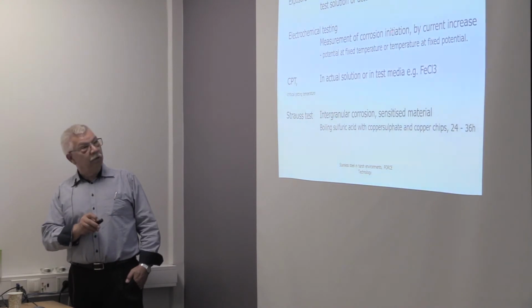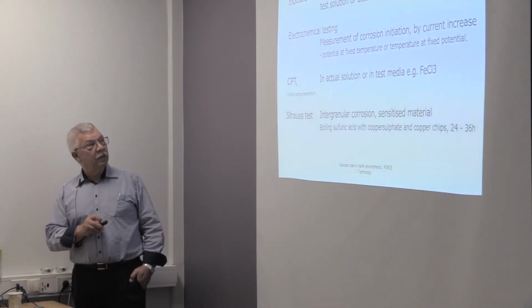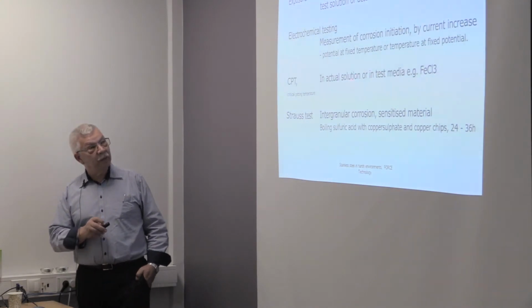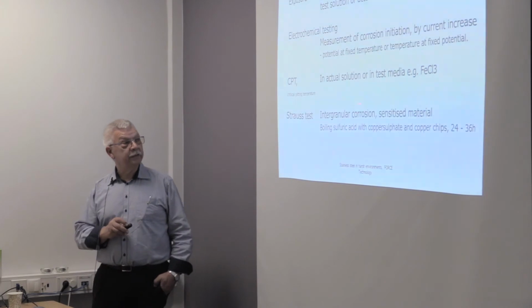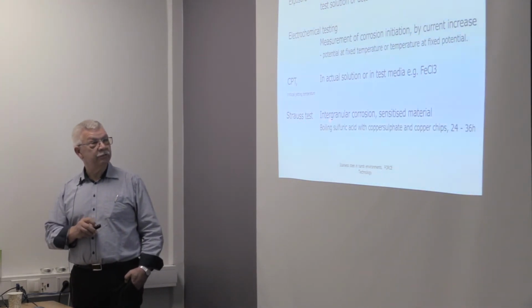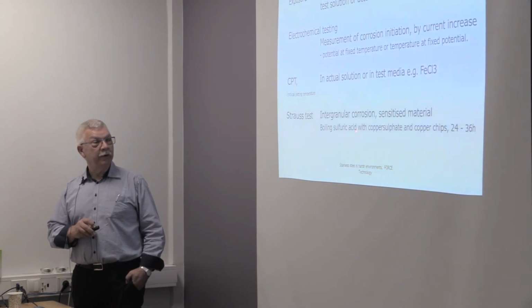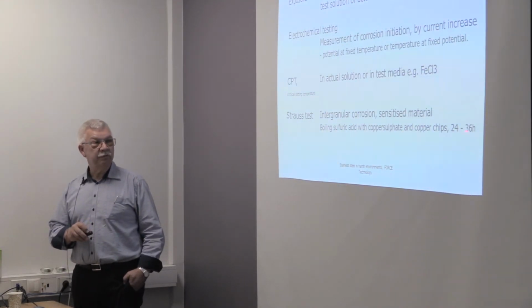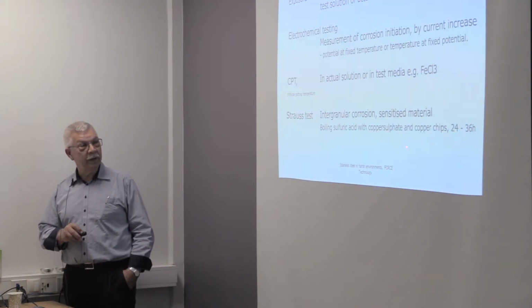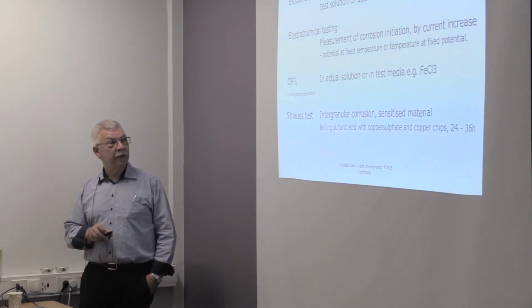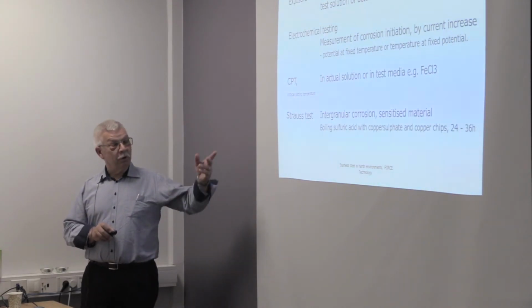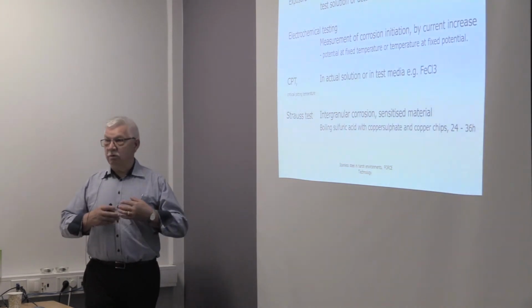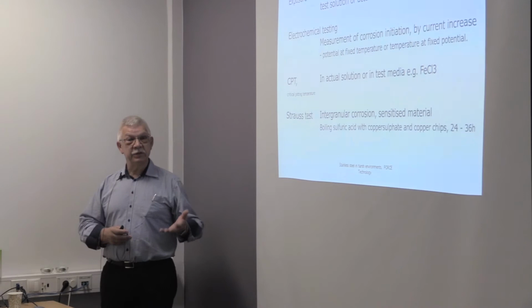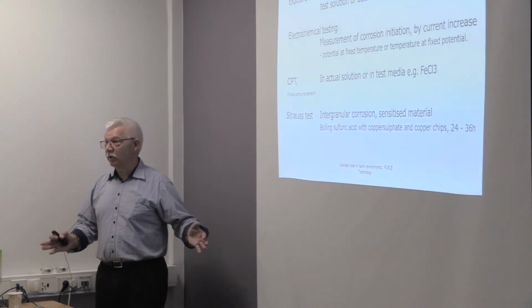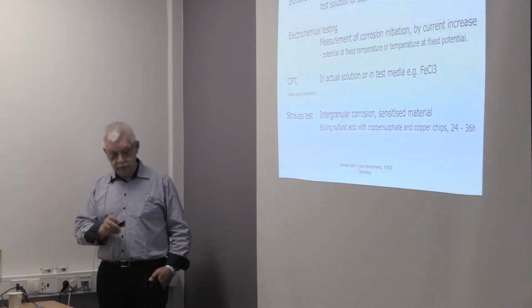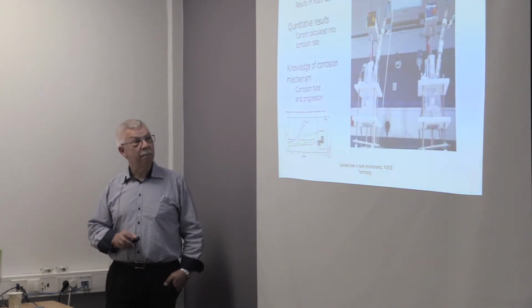We can do the ferric chloride test that we saw in the diagram before, test in actual media or this ferric chloride test. And we have the Strauss test for intergranular corrosion: boiling sulfuric acid, copper sulfate, copper chips, 24, 36 hours depending on which standard we apply, and then make a bend test to see if it cracks. And that's also possible if you have had some fire which would bring your material onto the critical temperatures for a number of hours. Then you can do a test afterwards to see if it has been damaged by this process.